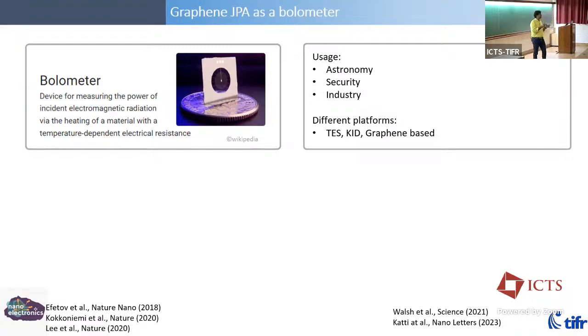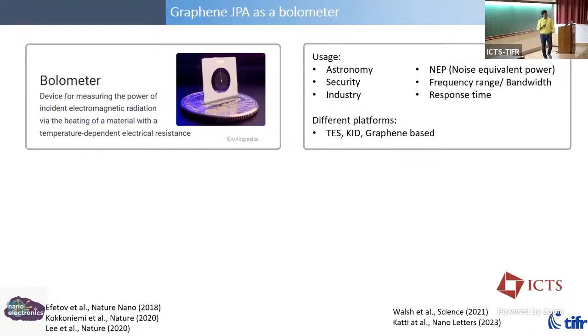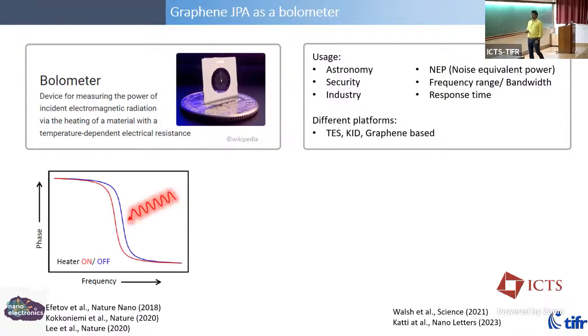Bolometers are devices which measure radiation or energy landing on them by different methods, different principles. Graphene is particularly interesting because it has a very low electronic specific heat, and the electron-phonon coupling is very poor at low temperatures. So if you dump energy into the electrons, they remain hot. And if you have some mechanism to sense those hot electrons, you have an exquisite sensor. That's where these bolometers come in.